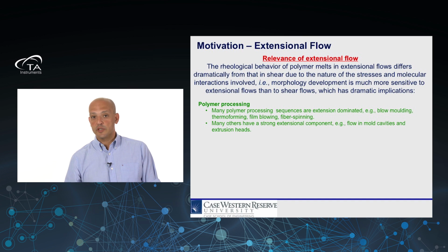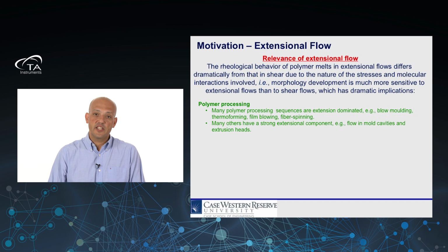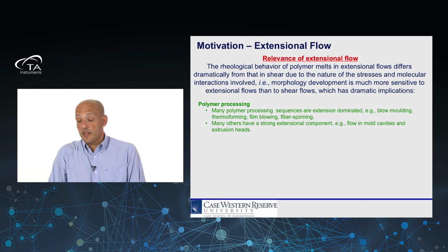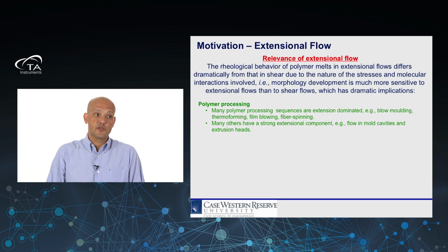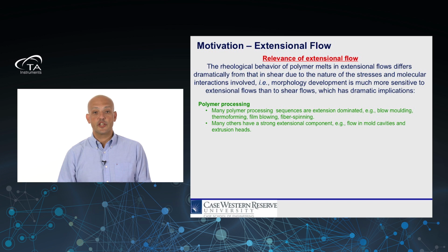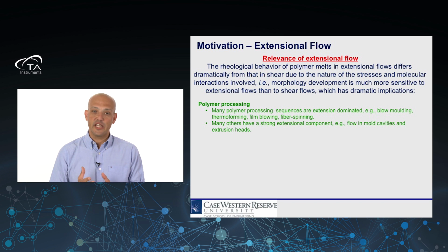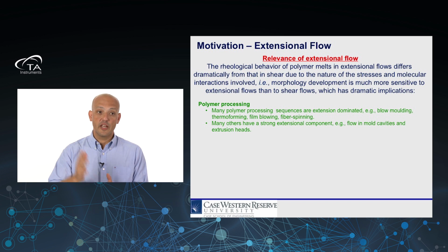Why are they so important? Well, the fact is that the rheological behavior of polymers, and most materials for that matter, but polymers in particular, in extensional flows differs dramatically from that in shear flows. And this is due to the nature of the stresses that are generated at the molecular level in the chains.